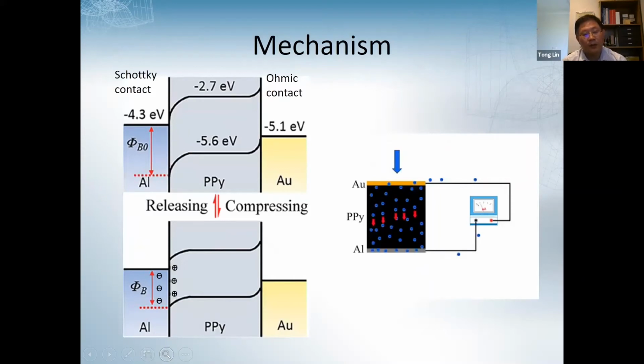For the Schottky junction, when PPy contacts the aluminum, they form a Schottky junction because PPy is a p-type semiconductor. So some electrons move from aluminum to the PPy layer, and the holes move from PPy to aluminum. So that reaches equilibrium. On compression, because of the barrier height reduction, some electrons move back to the aluminum layer, creating a difference in electrical potential at the interface. And because of the ohmic contact between PPy and gold, we can measure this electrical potential on the two electrodes.